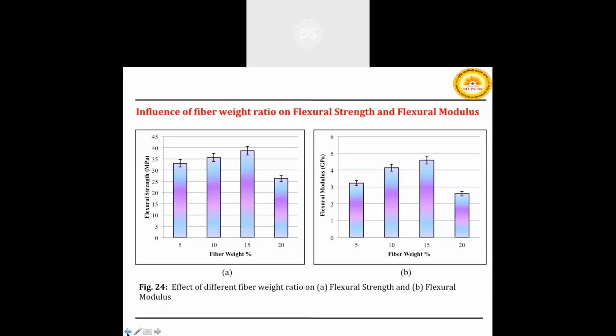The maximum flexural modulus of approximately 4.5 gigapascal was noted for a composite reinforced with 15% fiber weight ratio, which is 42% and 76% higher than 5% and 20% fiber weight reinforced composite respectively. The minimum value of flexural strength is 26 megapascal and flexural modulus is 2.6 gigapascal, obtained from the 20% weight ratio of the composite.